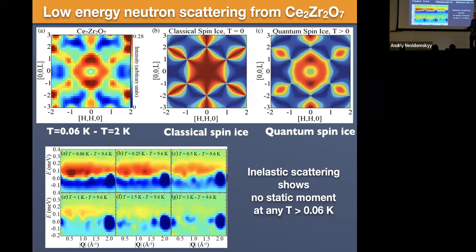But really what I want to do, I just want to see where the intensity is greater at low temperatures than it was at high temperatures. Okay, and these are all, I don't know how well you can read it, the difference in data sets between a low temperature and a high temperature. And what you can see is that there's basically no difference or very little difference in the elastic channel. But then as you go from the elastic position up to 0.2 meV, that's where the extra spectral weight resides.